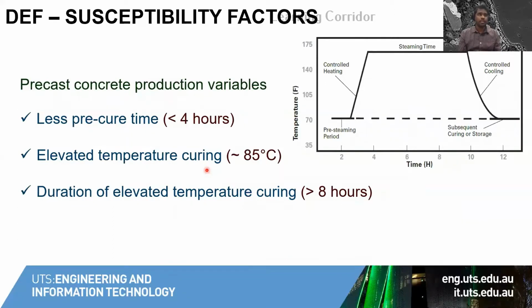First, we will see precast concrete production, where we already know the curing temperature forms the basis for delayed ettringite formation. Other than that, the pre-cure time is a very important factor, because if the pre-cure time is longer, which means the concrete is in ambient condition for a longer time, ettringite will form in the system, and then that has to be decomposed by the high heat curing temperature. Whereas if the pre-cure time is less,